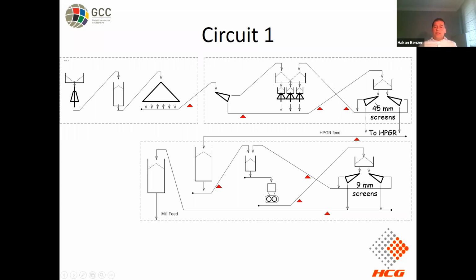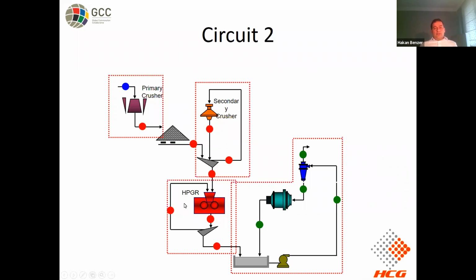Please be aware of the reduction ratio here, because I will show you some flow sheets again from the cement industry and what we can expect from the HPGR. Is this the right place that we use it, or can we improve it in the mining industry as well? Generally speaking, in most of the circuits, we are using the HPGRs as a tertiary crusher stage, replacing a very expensive cone crushing application, and feeding the ball mill. If you implement a high compression zone, you may reduce the Bond work index, which might be utilized as energy efficiency in the downstream ball milling operation, or the fines generated can be evaluated as a production increase. This is the only simple advantage that we could get in the mining industry.